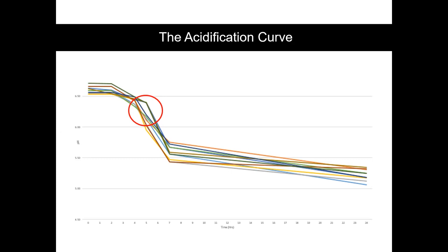If we look along the bar at the bottom, we find that this monitoring point is happening at about 5 hours into the cheese make. And at 5 hours in, I was pressing curds and getting ready to put them into the molds and put them on the press. If we can achieve a pH above 6.3 by the time the curds are pre-pressing, just before they go onto the cheese presses, then we're going to make a good Gouda. But if we're approaching 6.3 or we've gone beyond it, we're going to make a weak-bodied or over-acid cheese.